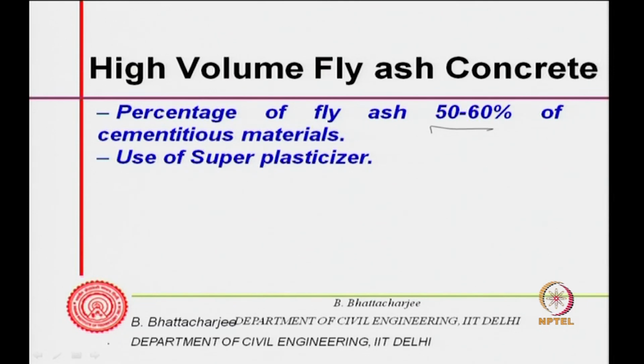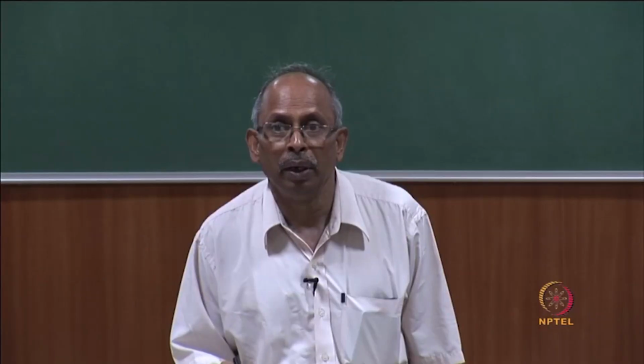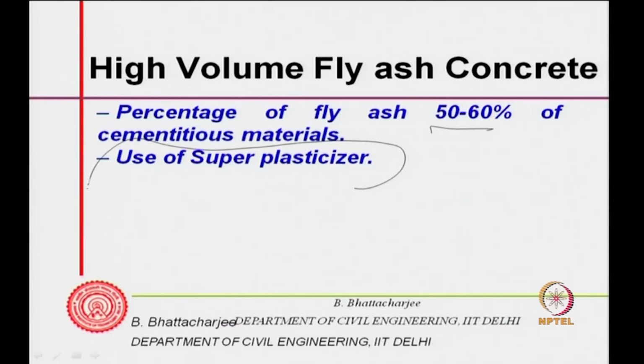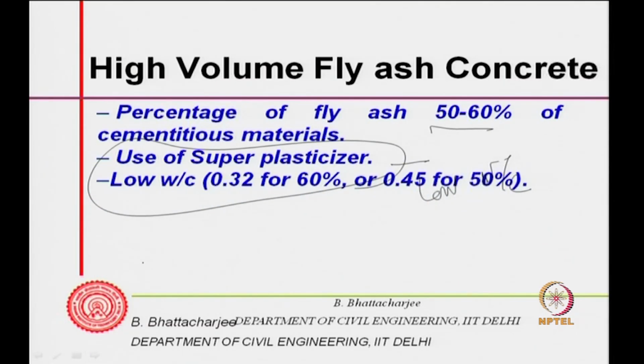But how do you use this? To get structural grade concrete of 20, 30, 40 MPa, use superplasticizer to cut down on your water and use a low water to cementitious ratio. So, therefore, initial strength will be given by the cement. So, 0.32 for 60% fly ash, 0.45 for 50% fly ash. So, use a low water to cement ratio, use a superplasticizer to get the workability.